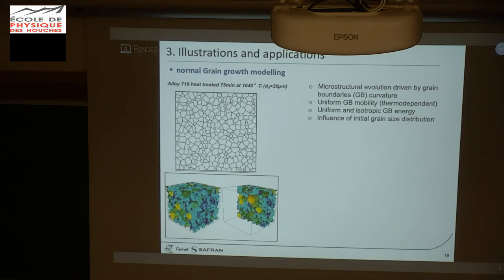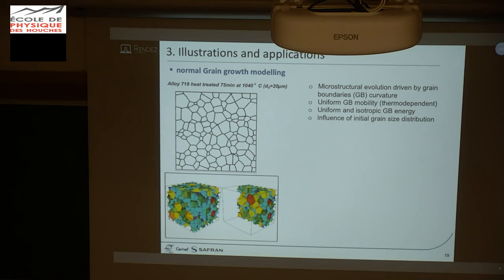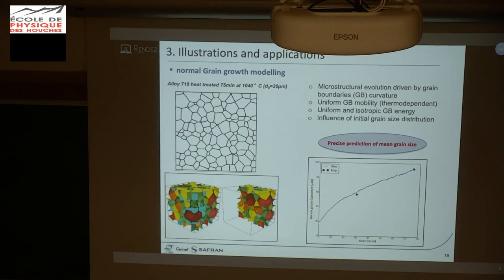Now, some validation of full field simulation, with comparison to experimental data. Here you have pure grain growth in subsolvus condition for Inconel 718, and this prediction was compared to experimental data from Aubert et Duval. This comparison was realized by Aubert et Duval and not directly by myself. And you can see the comparison of the prediction of the mean grain size of the 2D or 3D polycrystal compared to experimental data.